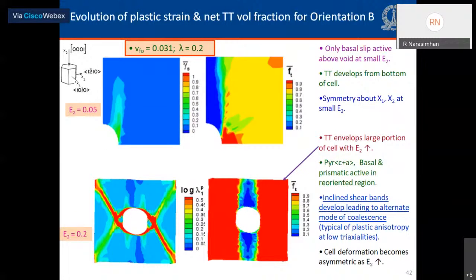These are contours of twin volume fraction and plastic slip corresponding to low stress ratio, again for orientation B. And again, at small strain, if you look at the contours at the top, in this case, basal slip and tensile twin are initially active. And as the strain increases, extension twins completely engulf a major portion of the cell. And one of the things that happens is that prismatic slip and pyramidal C plus A slip, which get triggered, lead to shear band induced coalescence as opposed to transverse ligament necking.